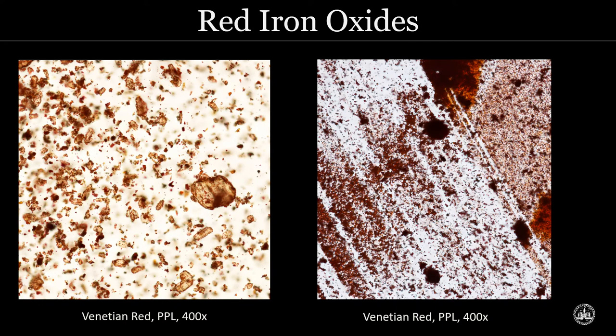So for instance, I had in my reference collection two examples of Venetian red. And the sample on the left appears to be the natural variety because we see these small red grains of hematite coating larger particles of silicate grains as well as other associated colorless minerals.